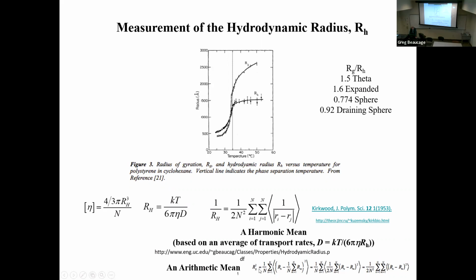We're actually looking at the moment of inertia of the mass, it could be weighted by the electron density for X-rays, the neutron cross-section for neutrons, or the index of refraction for light, right? So the weighting factor is going to be different, but basically it's a moment of inertia. Like you find the center of mass, find all the points, find the square of that average, and get the radius of gyration squared, right? So if you do polymer coil, it ends up that the separation distance is NL squared, so you can do that deal with this thing, right?